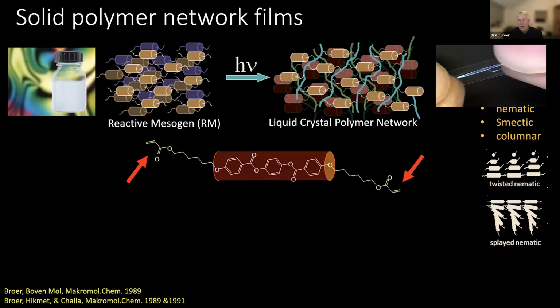Liquid crystal polymer networks are based on liquid crystal molecules, comparable to the molecules that, for instance, are present in your computer screen. But in this case, we have modified the molecules with polymerizable acrylate groups, in this case, two acrylate groups. Molecules can be aligned in their liquid state, just as is done in your television screen, by surfaces or by electrical fields. And in the aligned state, by a short UV exposure, with the presence of a very small amount of a photoinitiator that initiates the polymerization reactions of the acrylate groups, you end up with a densely cross-linked network that kept its order of the initial liquid crystalline state. But of course, it is now converted from liquid into a plastic film.